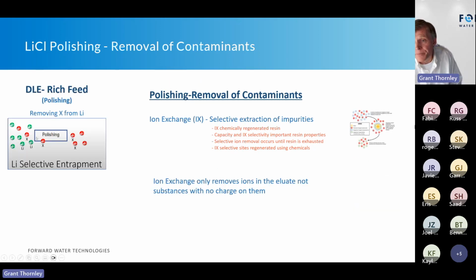So polishing removal by ion exchange depends on what we have. There are different types of resins available. The way that this works is that there's a charge, and it's going to go onto the resin, and whether it's a monovalent, a single charge, or a divalent will dictate the selection of the resin. But also, when you get down to trace versus bulk, there are some challenges associated with the selectivity of the contaminants being removed, and we'll get into that in a second.